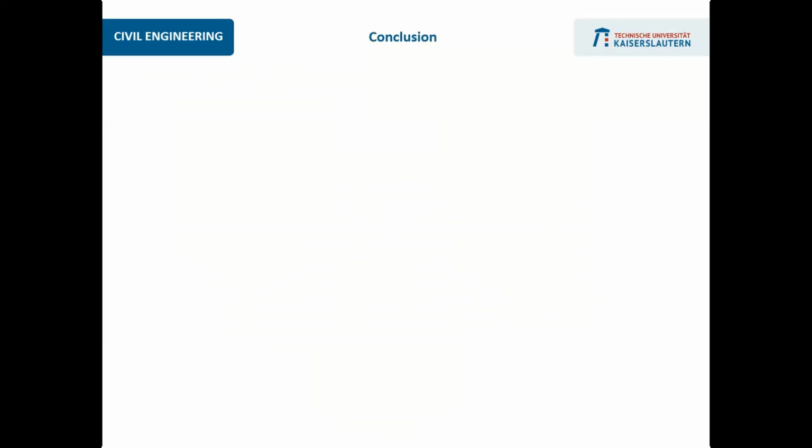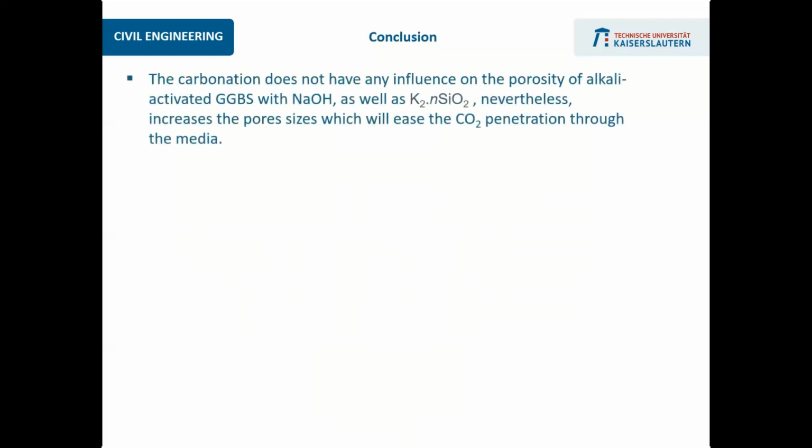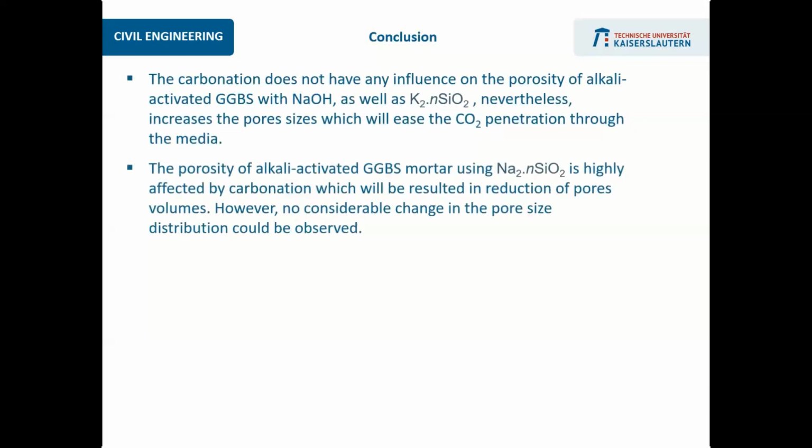Now I'm coming to the conclusion. The carbonation does not have any influence on the porosity of the alkali activated GGBS with sodium hydroxide and potassium silicate, but it increases the pore sizes, which will ease the CO2 penetration through the media. The porosity of alkali activated GGBS mortar using sodium silicate is highly affected by carbonation.